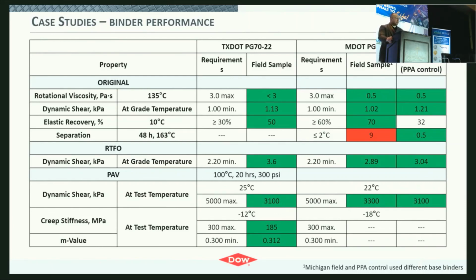From a separation standpoint, we did fail the field sample for the Michigan project, and we believe that's because of the mixed film. In this case, a mill was not used to process the polymer. It just was low shear mixing, and because of that, there was some particulate matter that was visible. We chose not to screen that out because it was there in the binder, and that's one hypothesis for why we were above the allowable separation test.